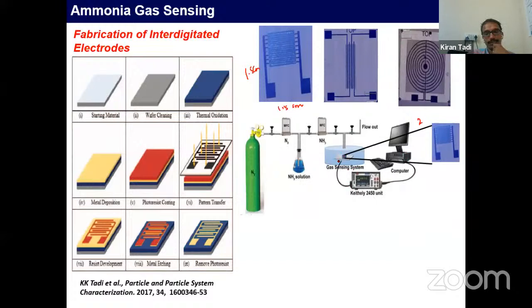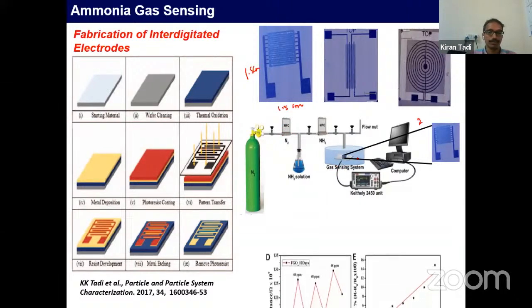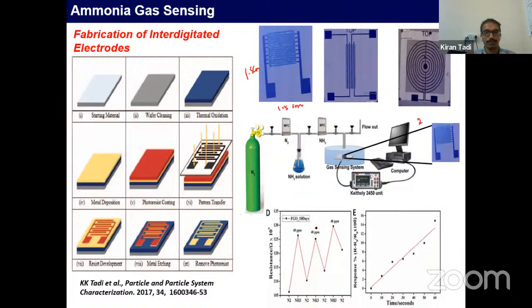This is a gas sensing system made using mass flow controllers, and direct gas sensing using these materials. There is nice reproducibility observed when 50 ppm of the gas is inserted. The electrode charge transfer resistance increases, which is a chem resistor based sensor, not an impedance based sensor, but an electronic chem resistor sensor. The resistance comes down when we go back to nitrogen gas alone.